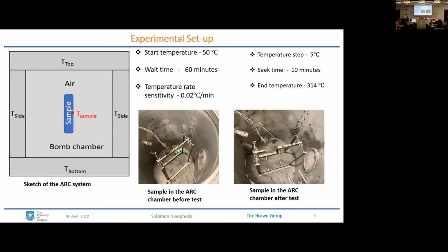So, I started the test from 50 degrees Celsius. From literature it is clear that thermal runaway occurs above this, and I started a little lower to track. The temperature step was 5 degrees, which is small enough to figure out exactly the point where the battery itself starts heating. And then the wait time was 60 minutes and the seek time was 10 minutes.